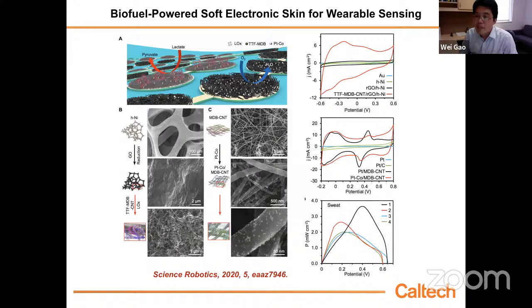And even at a lower level, for some people who have lower lactic acid levels, we can still get around 2 milliwatt per centimeter square. As you can imagine, if you increase the surface area, you can get higher power. And this is a continuous power.